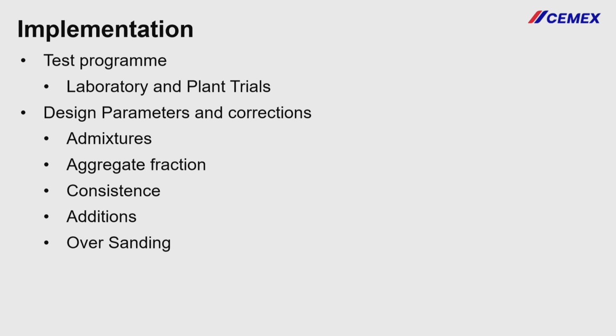Yeah, you want a C28/35 concrete. I design that probably to be a 42. I really don't want it to be a 43. So we're focusing very much on excess of design. So these corrections come into play. And then oversanding. We typically work on 4 and 8% oversanding, but can I be 3 and 7? If I'm 3 and 7, I need less water than 4 and 8, therefore I need less cement. So again, it all builds to reductions in CO2.